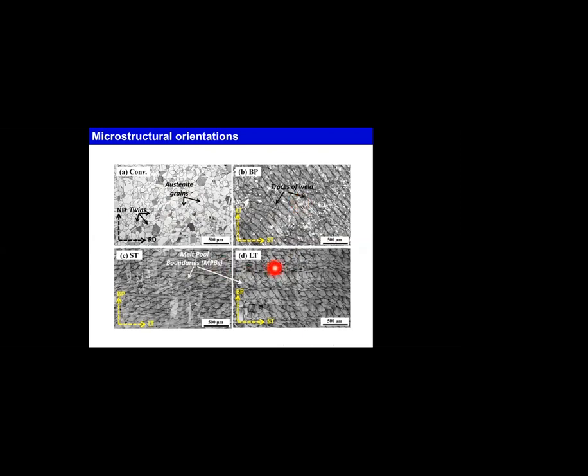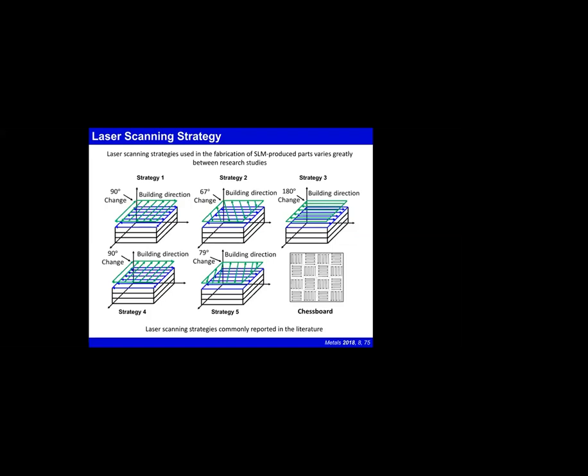What happens is that different microstructures in different directions give rise to a kind of directionality in the material. This directionality in the material generally is not good for the mechanical properties, or it may give rise to anisotropy in the material. And this is why, for metallic components which are load bearing, there are some issues which have to be dealt with, through proper control of the parameters and proper knowledge of the effect of the process parameters on the microstructure. So to address these problems, people devised different ways of using lasers.